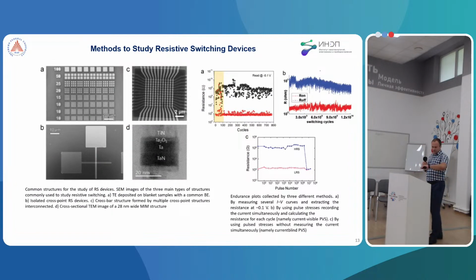When we produce different memristive structures, we also need methods to measure the resistive switching device. Here I present common structures for studying this class of devices. Here we see SEM images of three main types. This is top electrodes deposited on blanket samples with a common bottom electrode. On A. On B, we can see a cross-point resistive device. And on C, we can see a crossbar structure formed by multiple cross-point structures interconnected.